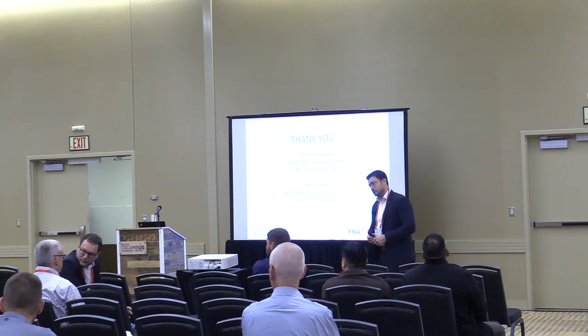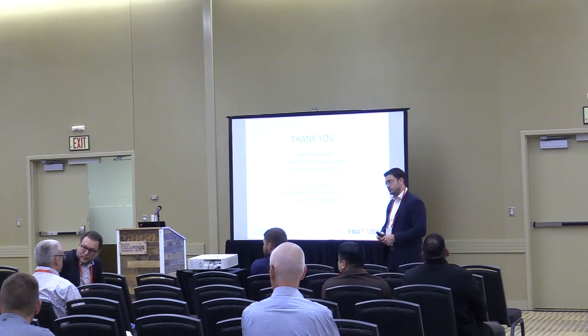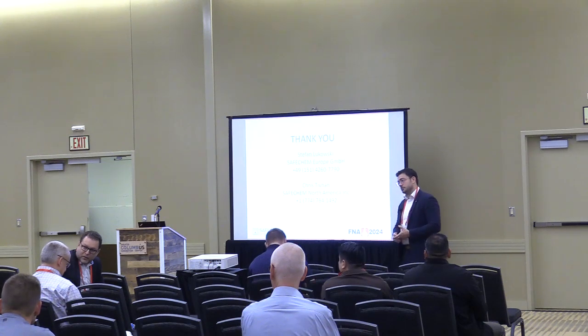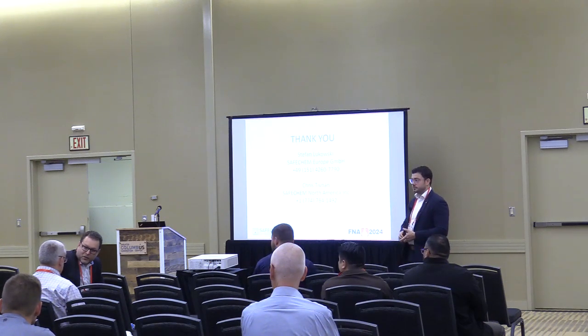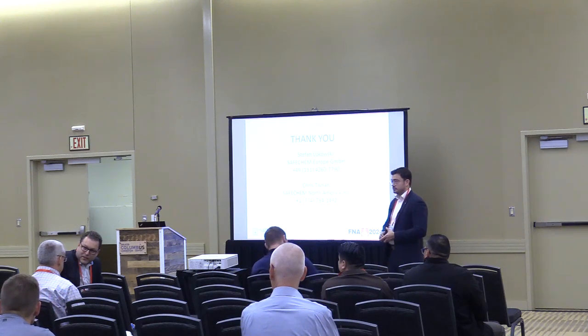If you wanted to use one of these for post-cleaning in an oil quench situation, what dynamics change as far as the ratio of solvents used and recovered in an oil quench situation? And does the machine change much if you're going to use it for pre-cleaning or post-cleaning because the contaminants and the loading is so different? The machines change a little bit because you got much more oil after the oil quenching process. So we invent a pre-spray process. So this means we use a couple of gallons of the solvent and we spray it on the batch.